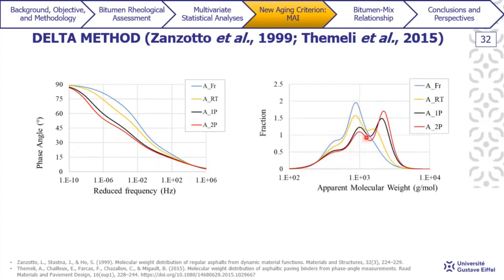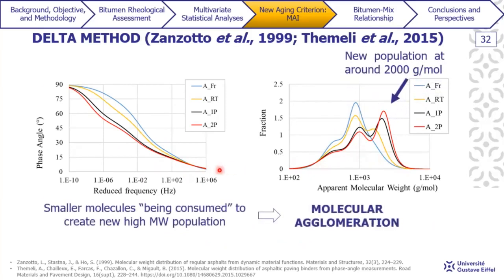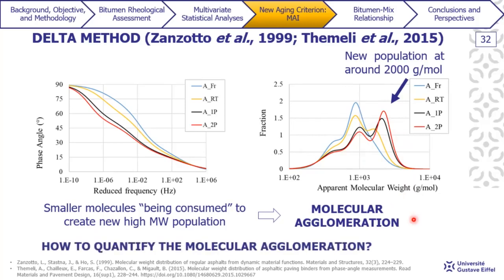The blue curve that represents the unaged bitumen seems to have this unimodal shaped curve here. And with aging, we can see that these small molecules seem to be consumed to create this new high molecular weight population here. We also have the peak of this new population at around 2000 grams per mole. In this case, this is believed to be molecular agglomeration. So the question was, how to quantify this molecular agglomeration?